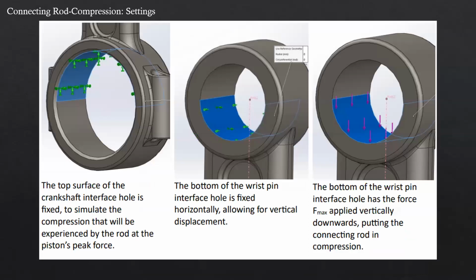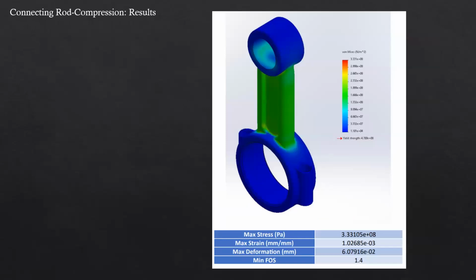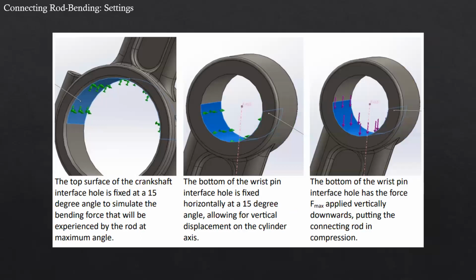Moving on to the compression. These are the settings for the compression of the connecting rod. The connecting rod material is 4340 steel that's also annealed. And if you look at the bottom of the wrist pin, its interface hole is fixed horizontally, and then the top surface of the crankshaft interface hole is fixed, and that's where we will be simulating the compression across those two sections. The results end up giving us a minimum factor of safety of 1.4, which is in line with where we wanted to be.